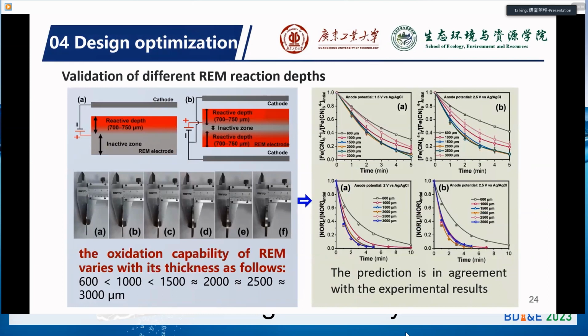around 1500 micrometer. So when the electrode thickness is below this value, when we increase the electrode thickness, the reaction rate increases. When the electrode thickness is larger than this critical value, the threshold, there will be no further increase of oxidation. So we can reduce the electrode materials this way.